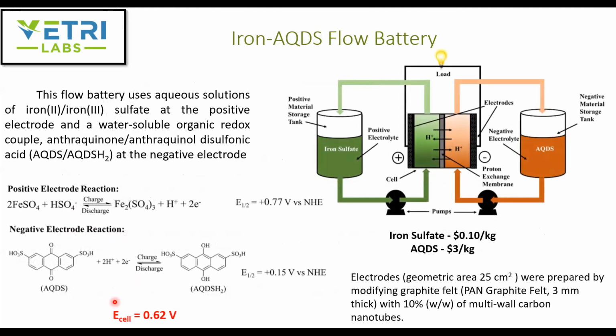So in this paper, they have proposed an Iron-AQDS battery. AQDS is anthraquinone disulfonic acid, or anthraquinol disulfonic acid. This is the first time this combination of Iron-AQDS flow battery has been reported. The iron source they have used is not iron chloride, as we saw in the earlier slide. They have used iron sulfate, obtained from a steel plant from scale removal. The cost of iron sulfate is around 10 cents per kilogram. And they have also used AQDS, and the cost comes to around $3 per kilogram.